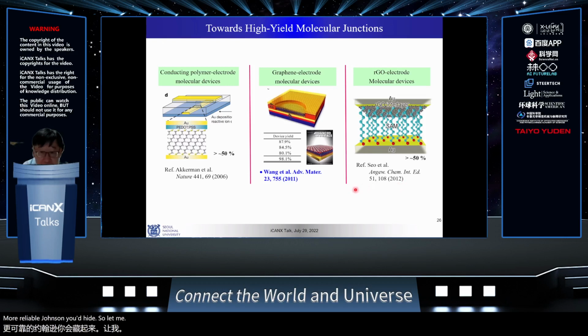Let me explain some methods to produce high yield. Nowadays, researchers studying molecular junctions are working on high yield. The first idea was demonstrated by a European group, who simply deposited a conducting polymer, PEDOT:PSS. That polymer is softly touched down with a solution process on top of the molecule. It is not to scale: the molecule thickness is about 2 nanometers, and the PEDOT:PSS is about 100 nanometers. But this PEDOT:PSS provides an interlayer electrode on top of the molecule.